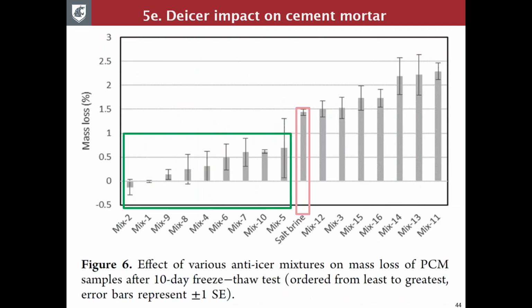Now, if we look at impact on cement mortar, starting from mass loss, again, statistically speaking, there are a number of products or mixed designs that feature much less scaling loss. And we also did some multi-regression analysis. Turns out the beneficial constituent to protect the cement mortar is the sugar beet leaf extract. The p-value is 0.12, which is not as good as less than 0.05, because typically when we define whether or not something is statistically significant, we say p-value less than 0.05. But again, considering the experimental results, this basically gives us roughly 88% confidence that the sugar beet leaf extract was protecting the cement mortar. And these are consistent with the literature that the organic amines and phosphates tend to be beneficial to the freeze-salt durability of mortars or cement concretes.